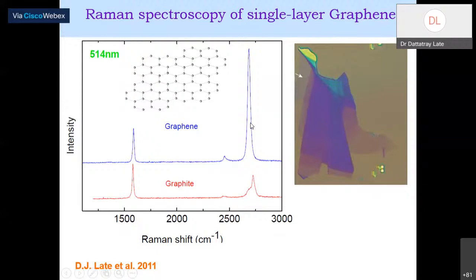This band appears because of the laser frequency which you have used, and also because of the number of layers present in your graphene sample. For example, you can see the graphite, this red spectra. You can see this 2D band is there. Do you see the intensity of this particular G band and 2D band? How much difference is there? A lot of difference. Here the G band intensity is too high, and here it's too low. In monolayer graphene, the 2D intensity is almost 3 to 4 times that of the G band.